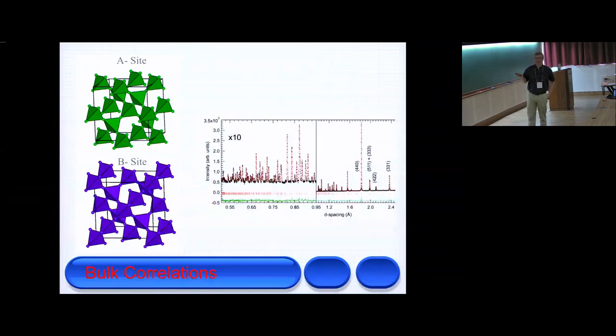And you'll do diffraction, and both samples will look perfect. It's only when you get to the fine details of all these spin-to-spin bond lengths being exactly the same. If there's any small difference, the energy scales that we're talking about in quantum liquids or in frustrated magnets are all roughly the same. So you change one by 2%, it changes the physics of the system. There are many examples that excite the community, but also give a bad impression to others who are just reading the literature, and they say, what's really going on in terbium titanate, for instance, because I've got 10 papers here with 10 different answers.